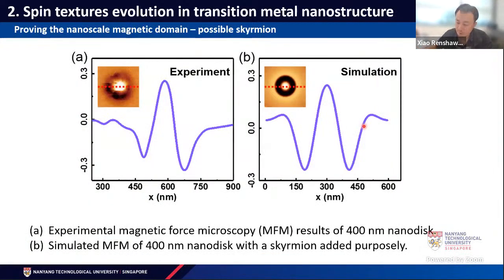Next, we are dealing with these skyrmion-like magnetic features. So we have to make sure that it is indeed at least close to a skyrmion. So we did a simulation of how the magnetization would look if it is a skyrmion, and how it would appear in a magnetic force microscopy image. On the right side is the simulation result. On the left side is the experimental result. As you can see, based on the experimental and simulation results, we have a skyrmion-like magnetic structure.